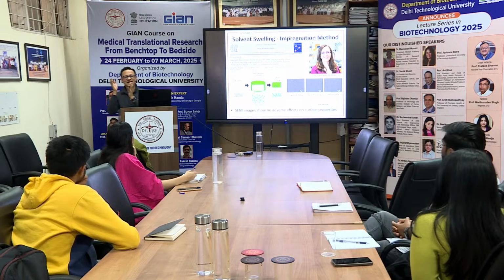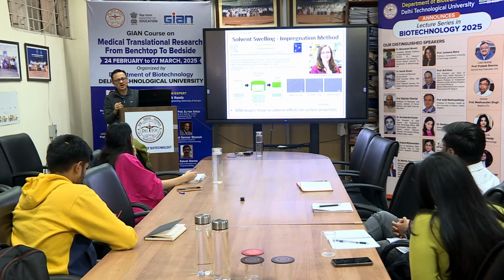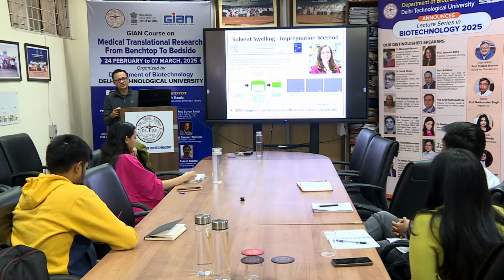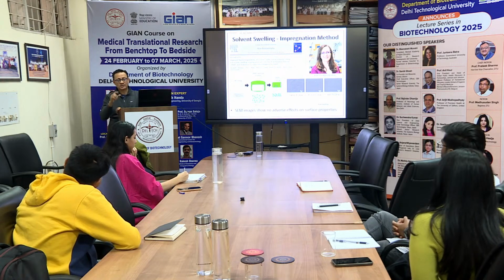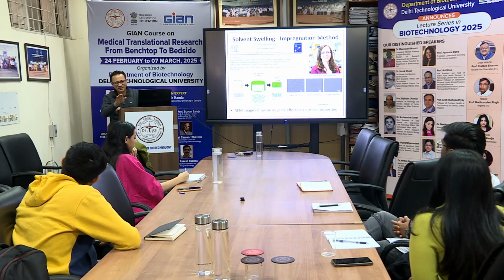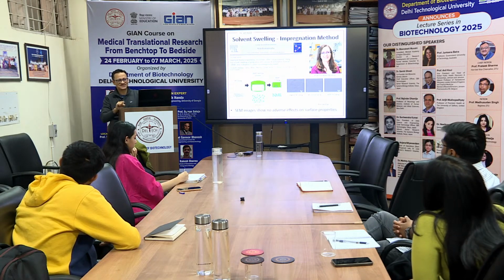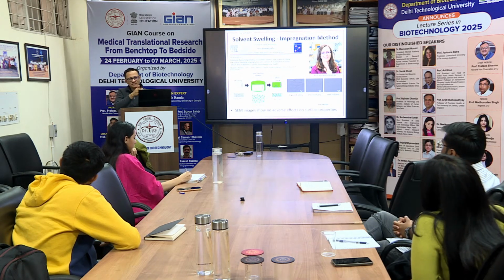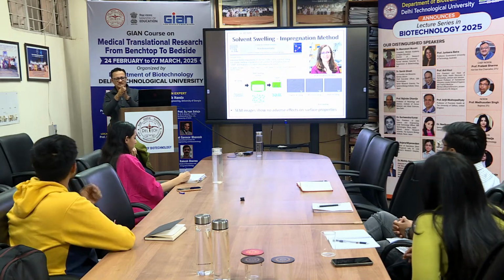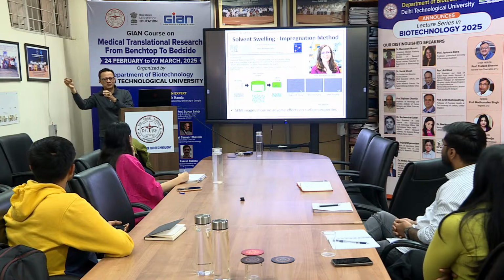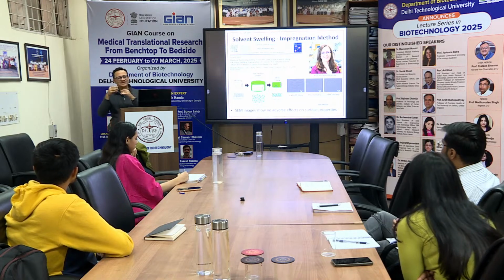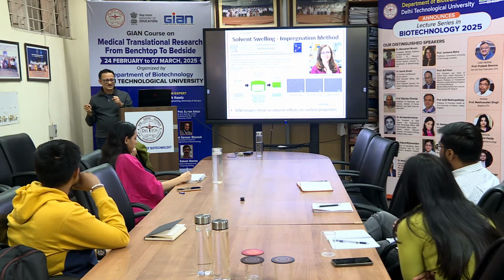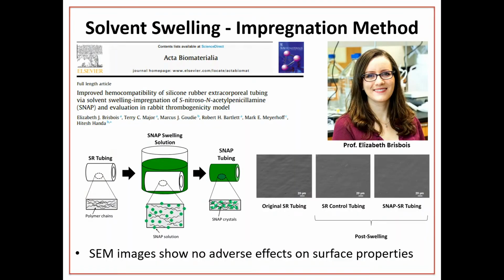So since you started that conversation, we also found out if we put up to 5 weight% SNAP, it does not crystallize. But after that, some amount, 4 or 5 or 6 weight% SNAP by weight, so 95% polymer or 90% polymer, that's the quantity you need for the crystals to start forming. So we are making sure that we use quantity in that range.